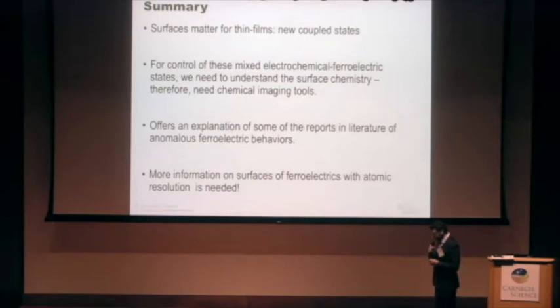Our time-resolved Kelvin probe force microscopy experiments suggest that there can be some really fast processes and some rather slow ones. It might be on the order of seconds. You could take, for example, lateral electrodes, bias them, and see a transport of charged species from Kelvin probe force microscopy studies, and they clearly show slower time scales. But in general, I assume there are both fast and slow processes here, and our KPFM studies can only go down to a few tens of microseconds. If it's anything below that, at a really local scale, we won't be able to measure it with our existing techniques.